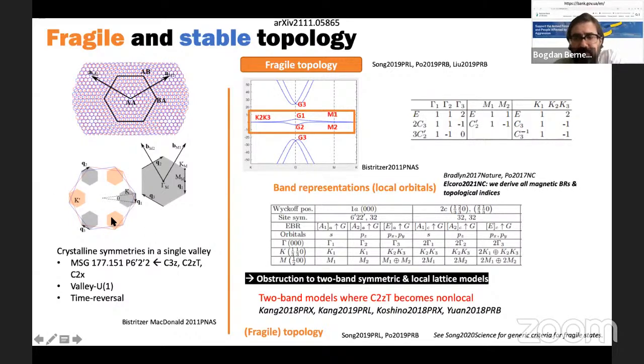So normally, if I have a flat band, I could potentially think that it comes from localized electrons, which do not tunnel to each other from side to side. So very localized electrons will certainly have a flat band because there's no tunneling, there's no bandwidth. Now, why is there a problem to describe the flat bands in the Bistritzer-MacDonald model or in the model of twisted bilayer graphene in this way? The problem is because of something that's been discovered in the past 15, 20 years, and this is topology. And to understand this, we have to look at the symmetries of the Bistritzer-MacDonald model. So I'm going to go through this a little bit fast, but it's not entirely necessary to understand all the symmetries, but it's good to get a hint of it.